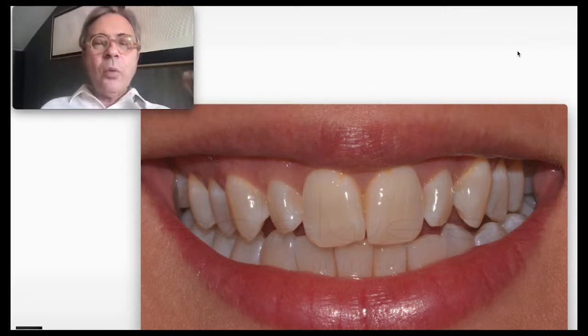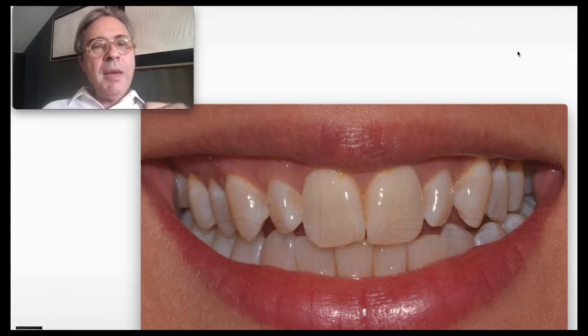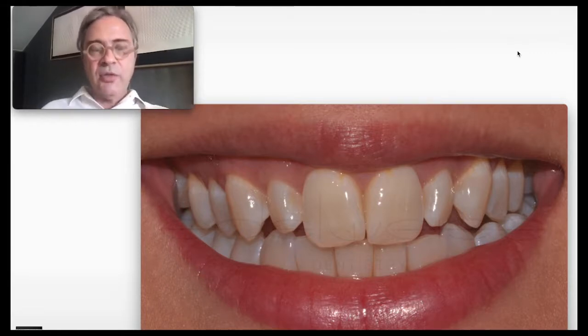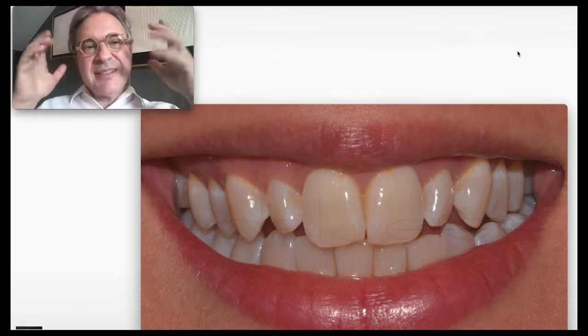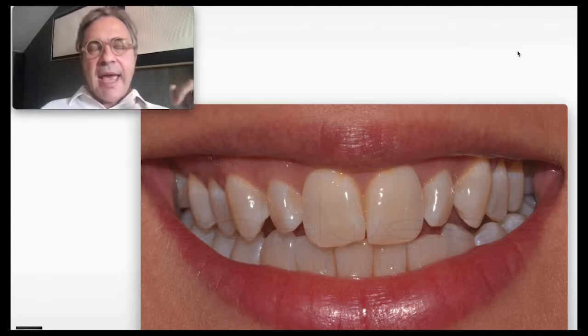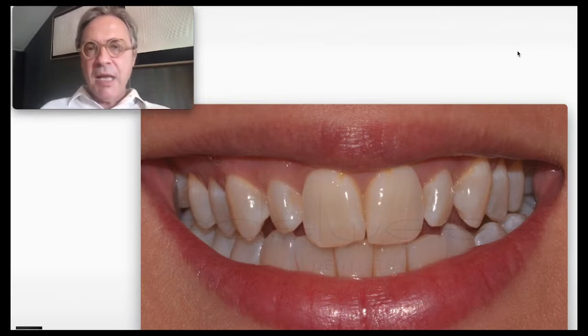However, when the first Edelweiss toolbox arrived in the office, I thought, well, maybe this is a technique for Valeria. If I could only make this Edelweiss veneer thin enough to bond it to her laterals with no tooth preparation. Now, as a general rule, composite veneer can be made thinner than a ceramic veneer because the material is less brittle and less fragile. And Edelweiss veneers are very thin. They are fabricated with an average thickness of about 0.5 millimeters. But you can make them even thinner if you like.